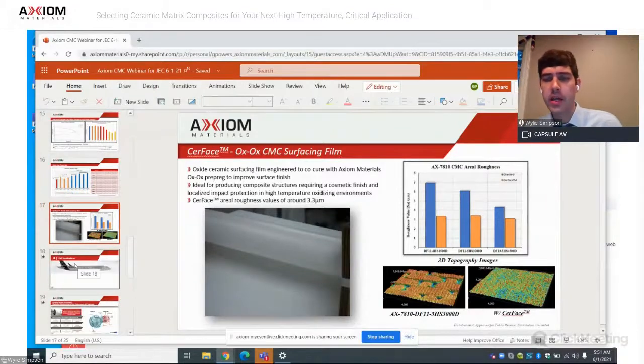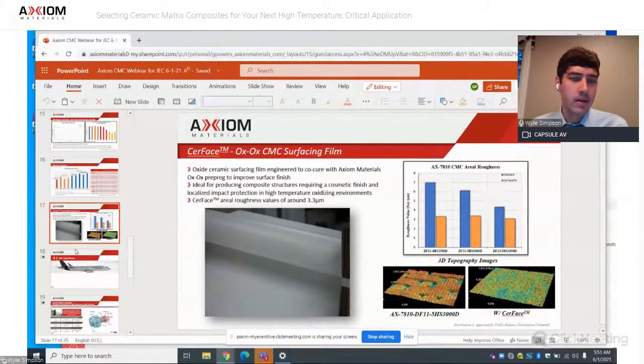So this is something that you'd cure to the surface of a component, maybe the first layer you lay down on your tool to really add some smoothness to your component. It also fills in some of the pores at that surface to help in maybe corrosion resistance or other penetration issues that happen with CMCs.